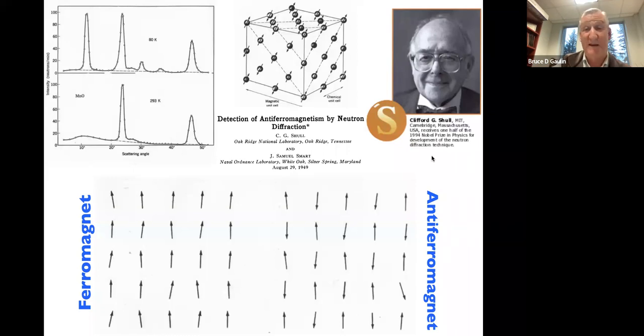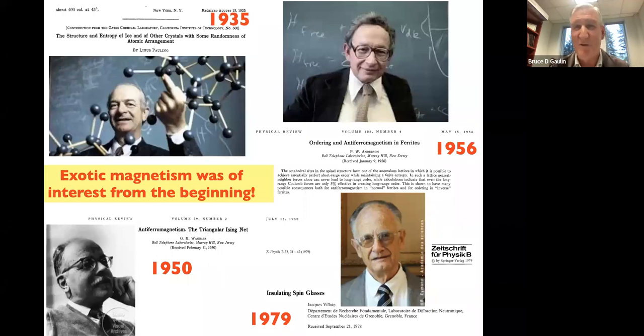Okay, and something kind of amusing and interesting is that no sooner had people found out or understood how to study conventional antiferromagnetic states, than they were already speculating about ways to generate an exotic, disordered state at low temperatures. At least initially, these exotic disordered states were themselves classical in nature. I'm just showing you some of the luminary theorists who worked on this problem very early on, including Gregory Wannier, who considered antiferromagnetism on a two-dimensional triangular lattice, and discovered that even classically you cannot get an ordered state down to zero temperature. And actually, that was in 1950.